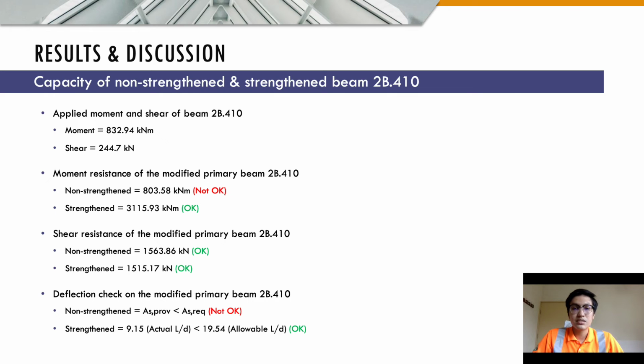3115.93 kN meters. The shear resistance for the non-strengthened beam is 1563.86 kN. The strengthened beam is 1515.17 kN. The deflection check on the non-strengthened beam has failed because the area of bars provided is less than the area of bars required, which halted the calculation of actual L over D. The strengthened beam has 9.15 for the actual L over D, which is less than the 19.54 allowable L over D.